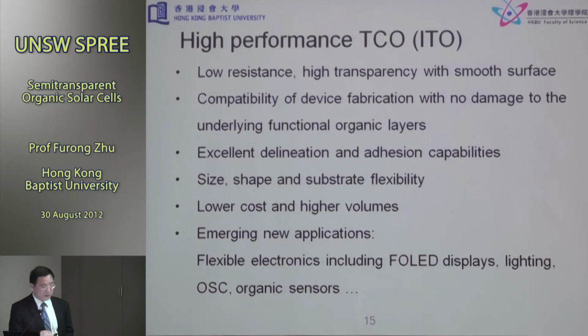So I need to talk about how to deposit or fabricate high-performance transparent conducting oxide materials. Essentially, for a highly conductive, high-quality interlayer that you use to connect the top and bottom cells in a tandem organic solar cell, these are the criteria, the technique you need. First of all, it has to be very conductive and very transparent, and has to be very smooth, because we know that the organic semiconductor layers, particularly in organic solar cells, are very thin. So if you have a spike, it will basically kill the device and create shorts in the solar cell.